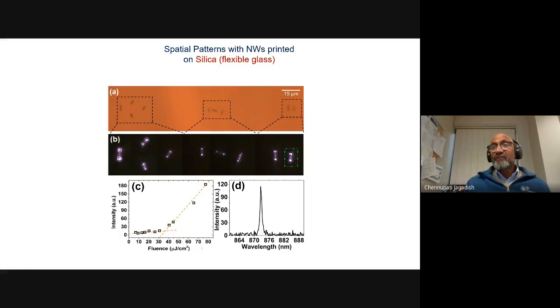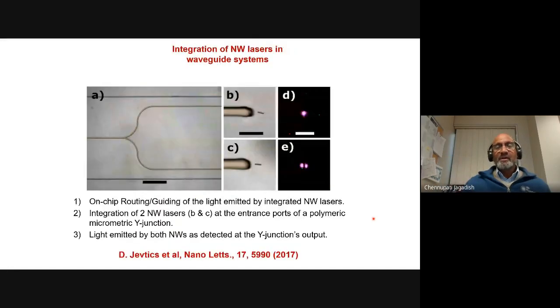And by the way, these are indium phosphide nanowire lasers. And then you can also get a beautiful light emission, indicating that this is a very good technique, and we'll now be able to precisely locate these nanowires wherever you want. So then we asked them, can you locate these nanowires in front of a waveguide? In fact, they have done that. They created these SU8 waveguides, put these nanowires, and were able to couple the light through the waveguide.